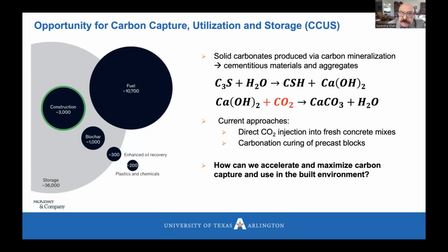and storage. If you look at the hydration reaction of one of the main components of cement, tricalcium silicate, C3S, when it hydrates, it produces calcium hydroxide. And if you inject CO2, it results in very useful calcium carbonate in the hydration product. Our objective is how can we accelerate and maximize carbon capture to use in a carbon-conscious built environment.